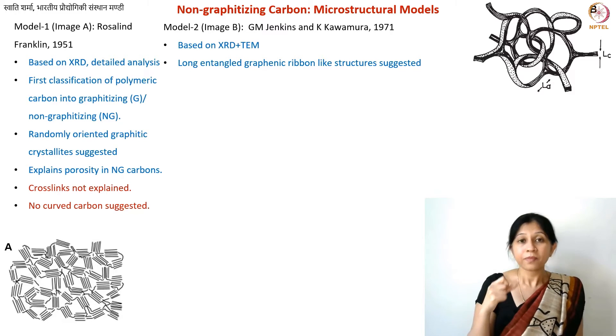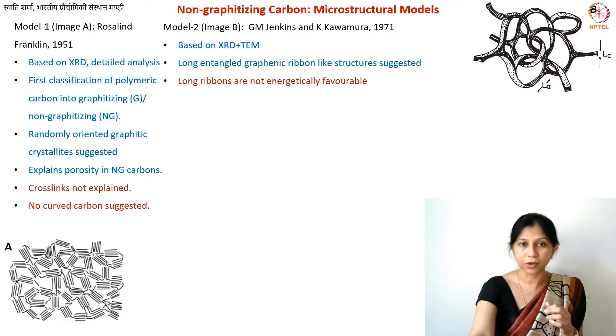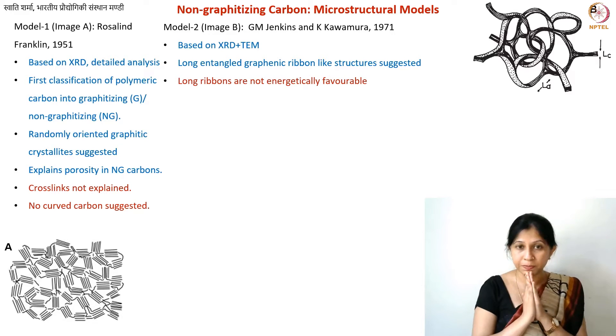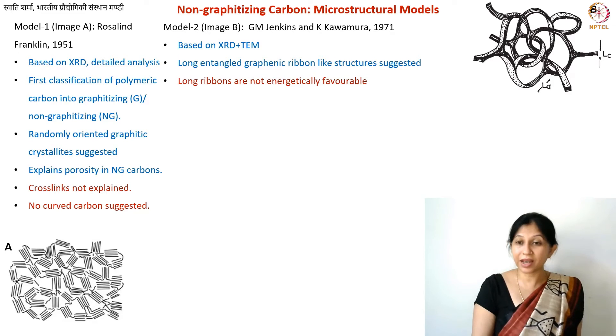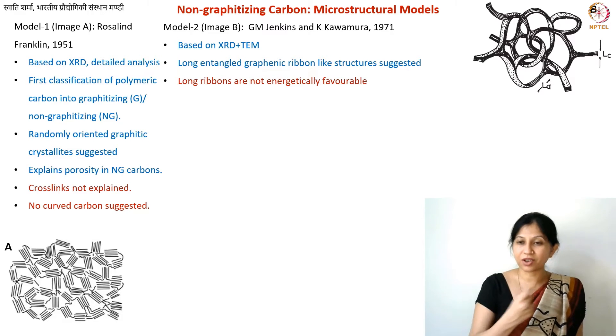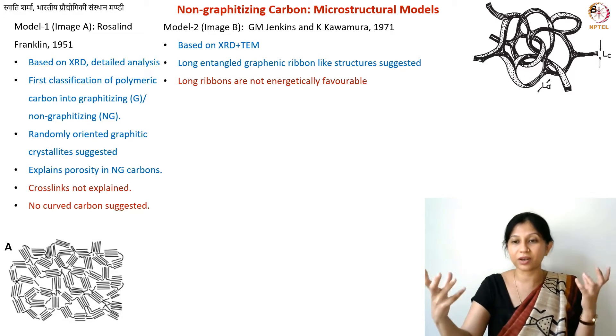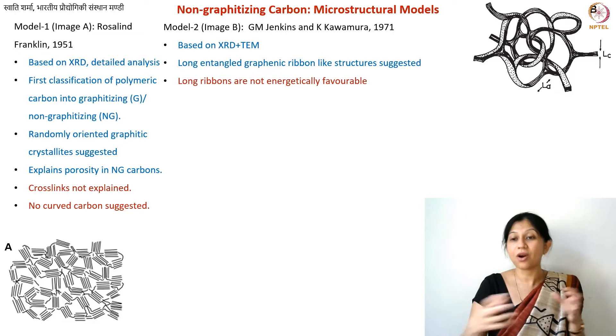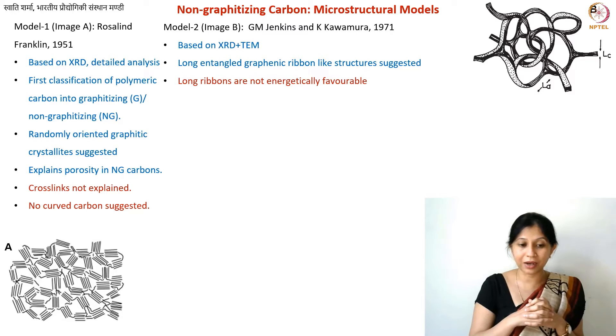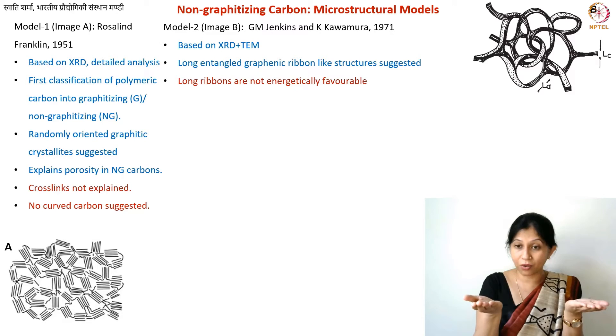One thing that was not very clear in this model was how to calculate La. Now the limitations: first, do you think it is possible to have such long ribbons of carbon? It is not energetically favorable to have such long ribbons. Some other models did suggest that ribbon-like geometry is possible because polymers have chains which lose their non-carbon atoms and convert into fiber or ribbon-like structures. However, how these ribbons also grow laterally, and if so, how long — that is still unclear.